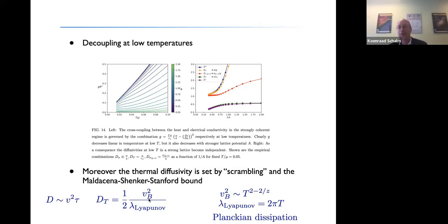And then in this particular case, the v_B squared in the system is also temperature dependent. It scales as T squared in the limit of z goes to infinity. What happens in the charge transport sector is still a big question. The charge transport sector does not scale as D ~ 1/T in this system, and we leave that open for further research. That was the same as was found in homogeneous lattices or holographic systems with large disorder. But the thermal diffusivity is completely explained in terms of the scrambling rate and the Lyapunov exponent of the system.